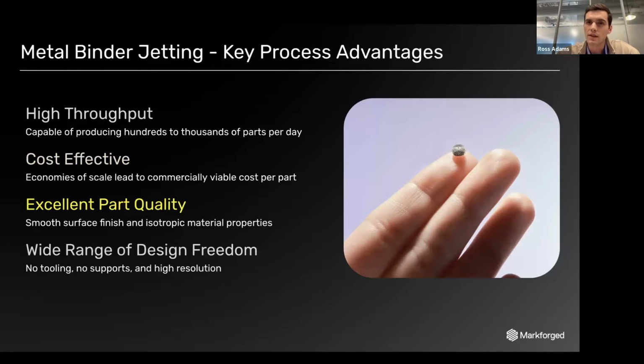And number 3 is going to be excellent part quality. The surface finish, the feature fidelity, you get really smooth surface finish, about 6 micron Ra values, and we can post-process that down to 1 micron to get really mirror surfaces. And the material properties, they're isotropic. They're uniform across the entire part. We are able to operate to the same standards of metal injection molding, MPIF 35, and that allows for much more predictability and repeatability of the integrity and the properties of the parts that you're getting, and having that scale across thousands of components. And then lastly is very wide range of design freedom.